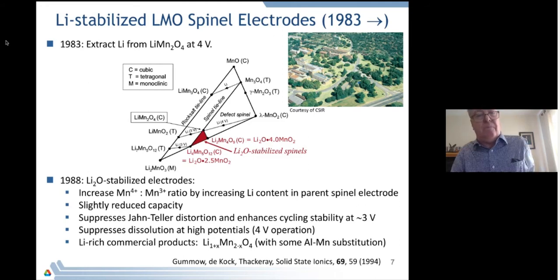So we jumped back on the bandwagon and looked at the lithium manganese oxide phase diagram in detail, and noticed some very important factors, that if you increase the manganese 4 manganese 3 ratio, you could do this by increasing the lithium content in the Spinel electrode. Although this slightly reduced the capacity of the electrode, it suppressed the Jahn-Teller distortion and enhanced cycling stability at 3 volts. It suppressed dissolution at high potentials and eventually found its way into lithium-rich commercial Spinel products.